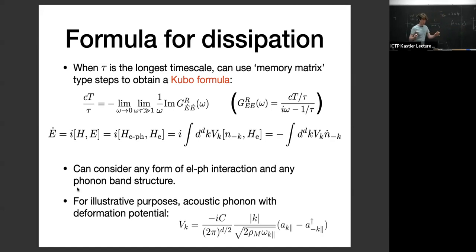When momentum decays much more slowly, then this time scale in the Drude formula is what Drude originally thought it was, which is the momentum relaxation rate. In a conventional metal, it's not the momentum relaxation rate. But if the metal is very, very clean, then it's the momentum relaxation rate. Then this formula can be directly related to a single slow quantity, which is the momentum.